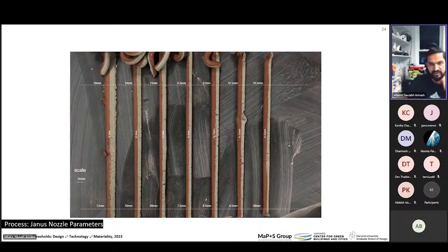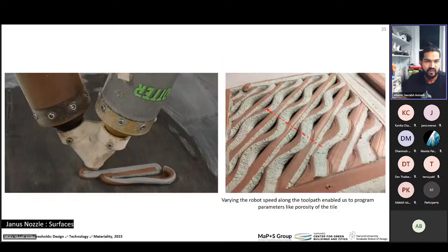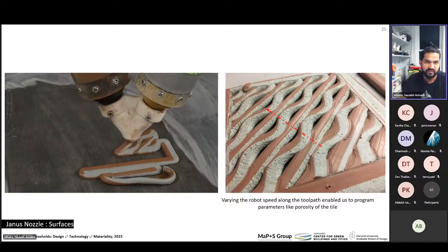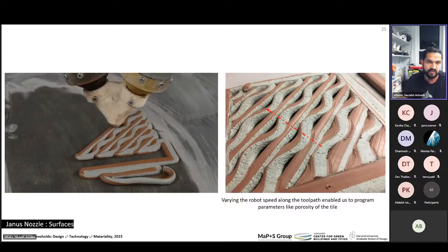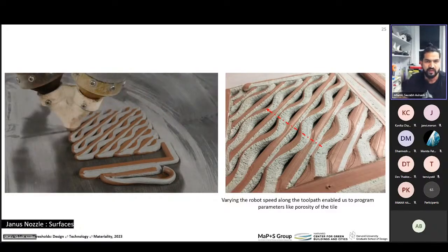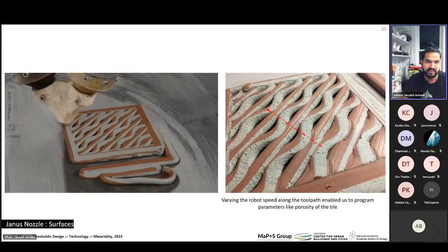Using the Janus nozzle, multiple tests were performed to explore the design space, to establish relationship between various parameters of extrusion like robot speed, layer height, bead width, extrusion rate. We tested different dimensions from lines to surfaces to solids. Once we got a hang of the parameters, we started testing them on flat toolpath objects. Using these objects, we also started testing the different relationships between the parameters.